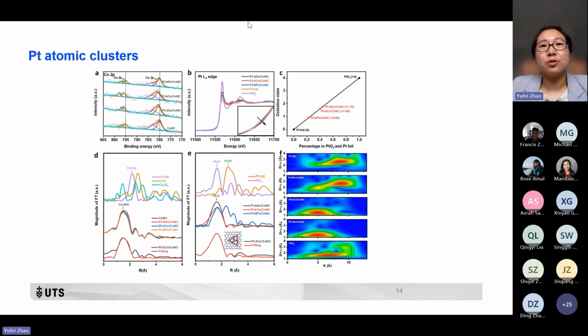And then for the electronic structure, we have done XPS. Besides synthesizing this atomic cluster, we have also prepared single atom and nanoparticles as comparison. For these different samples, compared with the pure cobalt single atom catalyst, the single atom and atomic clusters show a peak shift. That means after incorporating the single atom and atomic cluster of Pt, it formed an interaction with the substrate cobalt atoms. So the interactions between cobalt and platinum occurred to cause the peak shift.